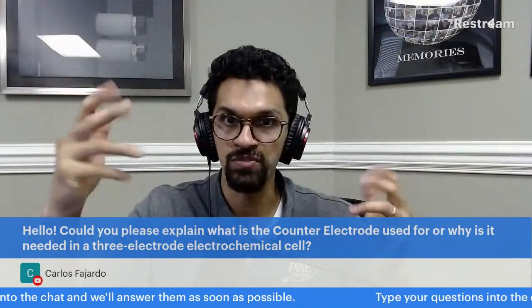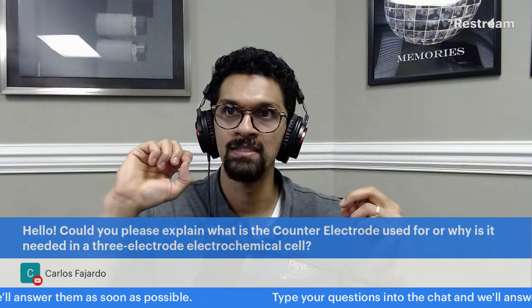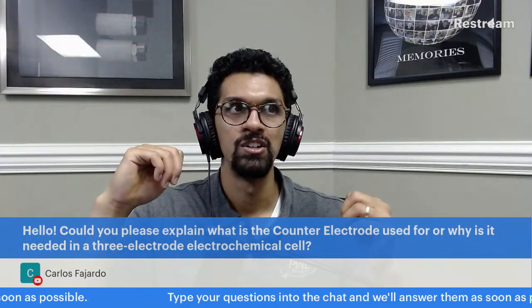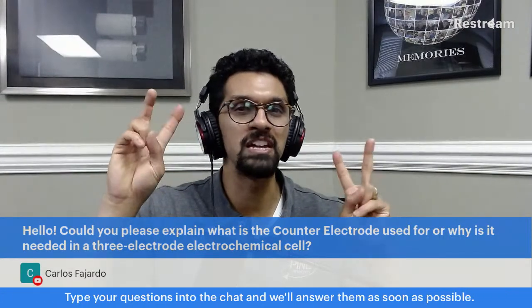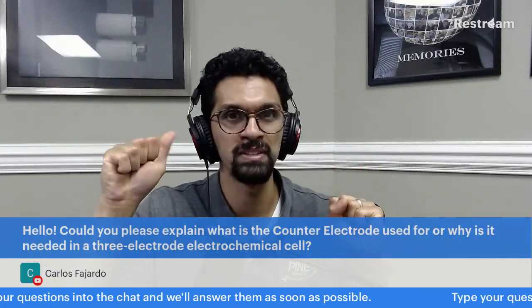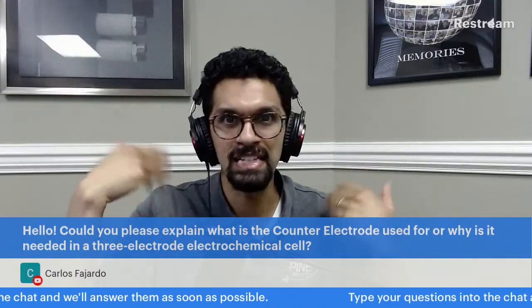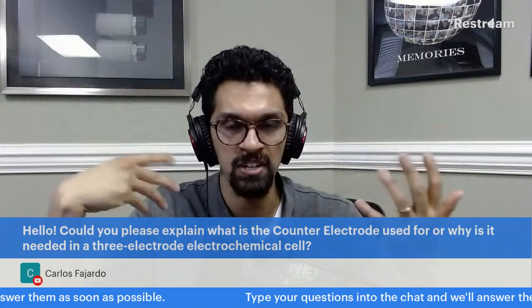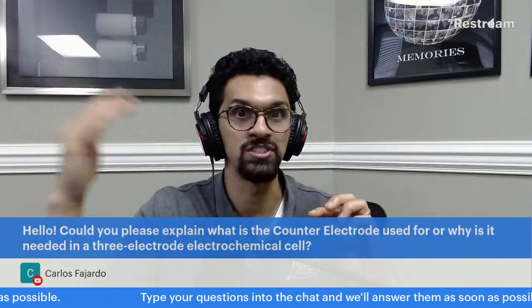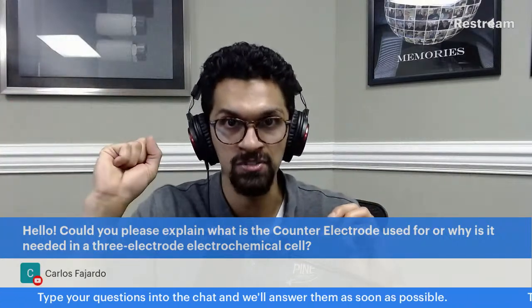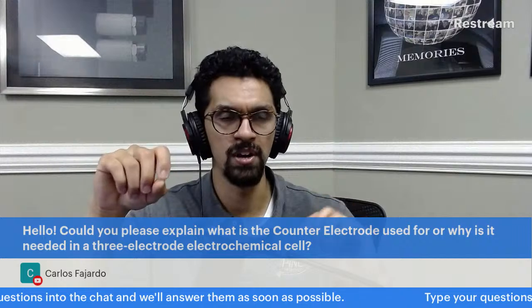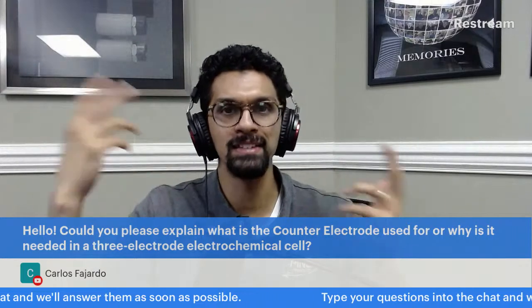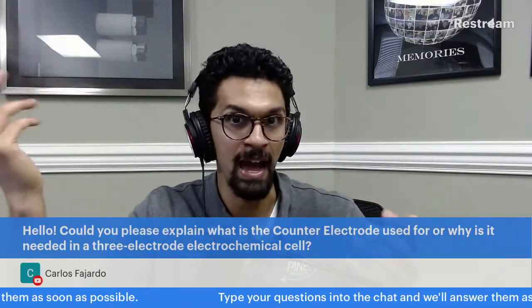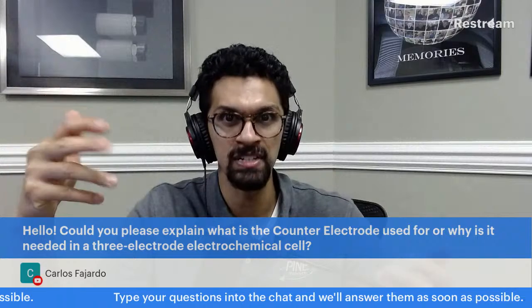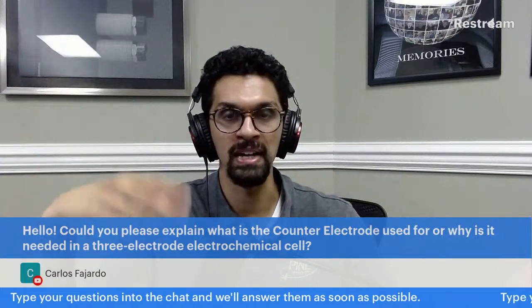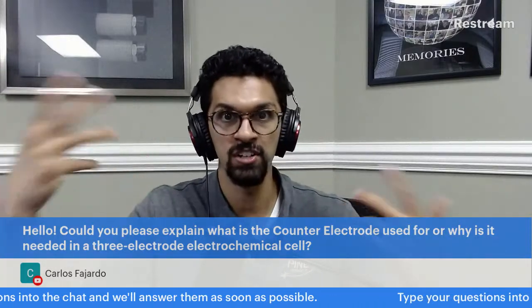and they have a larger surface area, and they also tend to be inert, which is a weird word, but active. They can easily undergo an oxidation or reduction reaction, whatever reaction is needed to drive your working electrode reaction. And so platinum is commonly used because platinum is very active. It doesn't take a lot of energy for platinum to generate an oxidation or a reduction current.